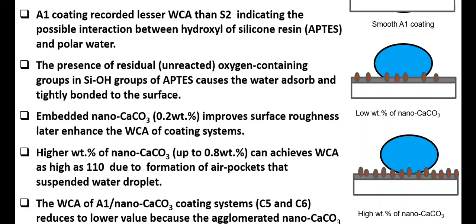The higher weight percent of nano calcium carbonate can achieve a water contact angle as high as 110 due to the formation of air pockets that suspend the water droplets and make the surface more hydrophobic. The water contact angle of the A1 and nano calcium carbonate coating systems C5 and C6 is lower because the agglomeration of nano calcium carbonate leaves narrow spaces, which causes low surface roughness. So at 0.8 weight percent of nano calcium carbonate, it shows the ideal, maximum air pockets. Beyond that, when we increase the nano calcium carbonate, agglomeration will tend to happen, and this agglomeration on the surface makes narrow surfaces and reduces the surface roughness.